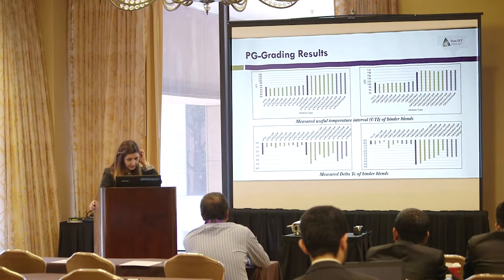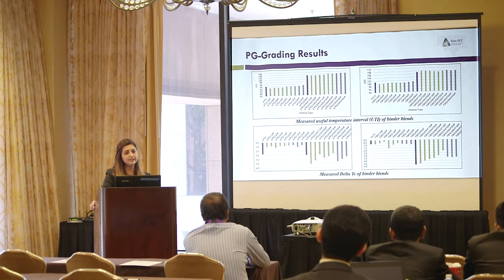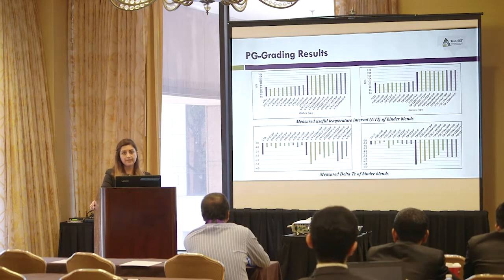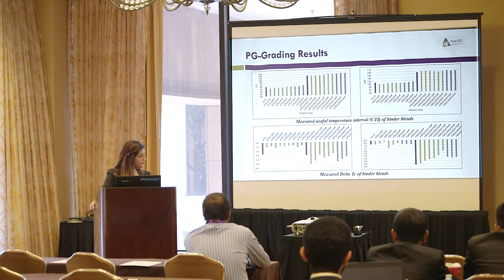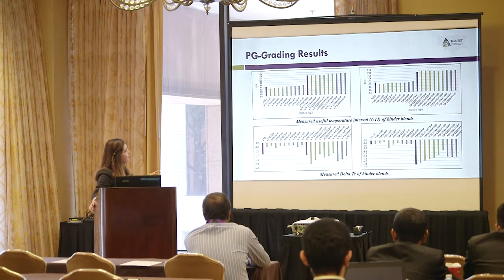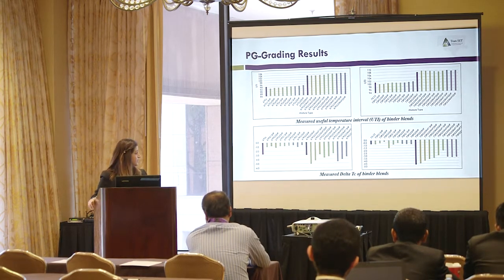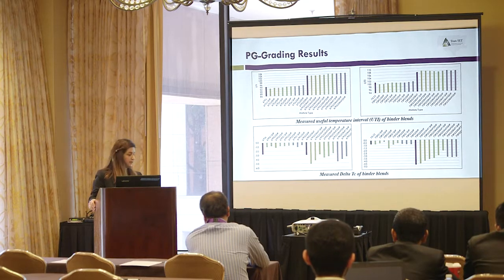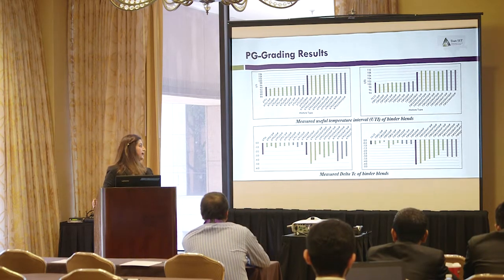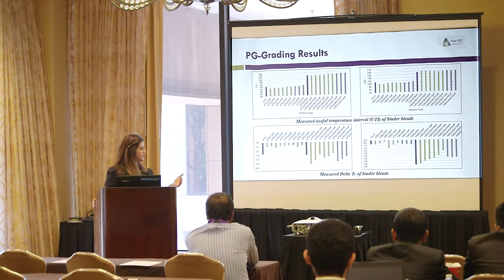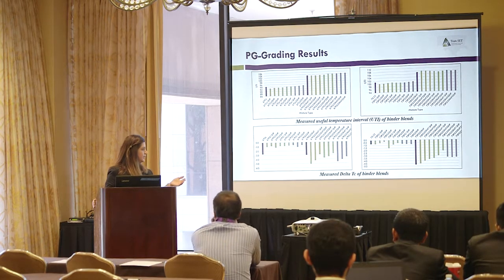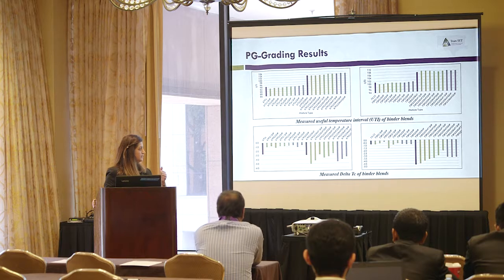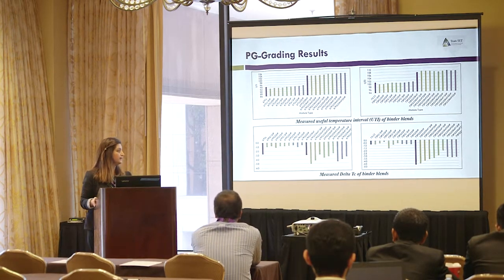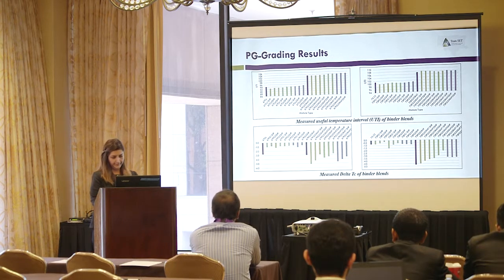We also have delta TC, which is the difference between the critical temperature for stiffness and the critical temperature for phase angle, or delta. As you can see again, we have an increase in delta TC with the addition of recycled material. And then we see another increase with adding 1% of self-healing polymer, but the delta TC decreased with an increase in the amount of self-healing polymer and then with UV exposure.